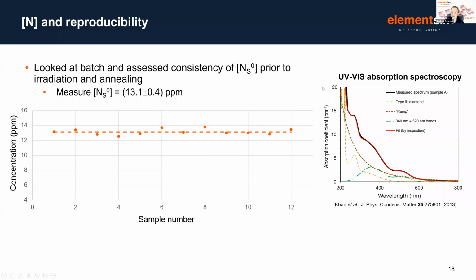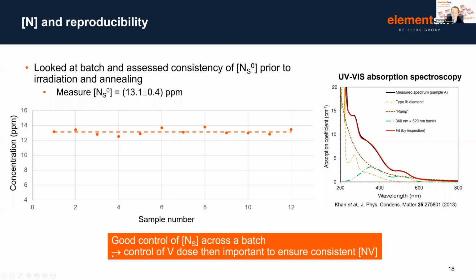And the technique that we use to make these measurements is simply absorption spectroscopy, UV-vis absorption spectroscopy. And really, there's a wealth of information that we can get by this spectroscopic technique over and above just simply the amount of nitrogen. So it's really by probing this spectrum in further detail that we can gain a greater insight in exactly the purity of this material in terms of both nitrogen and parasitic defects. So clearly from these initial results, we had good control of nitrogen across a batch of material.